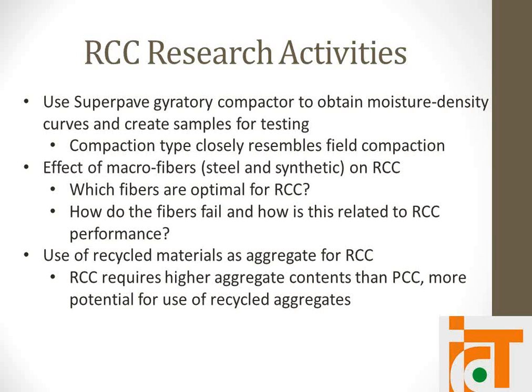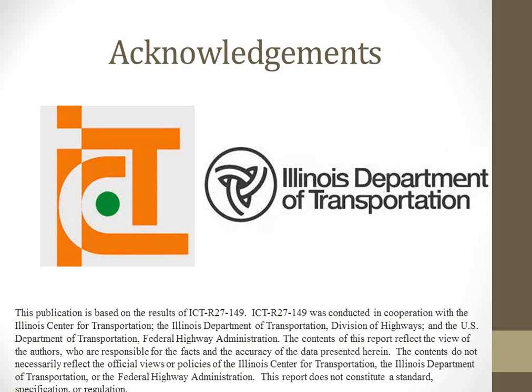Also want to look at fibers and their effect on RCC, since steel reinforcement isn't used, can't be used in RCC. We want to see how fibers will affect the toughness of RCC, as well as whether they can be used to increase the effectiveness of joints or even extend them. And we want to look at using recycled materials like RAP or RCA or steel slag in RCC. Since RCC has a lot more aggregate in it, we can get rid of more of those recycled materials by placing them in RCC. And I'd like to thank ICT and IDOT for funding this project.